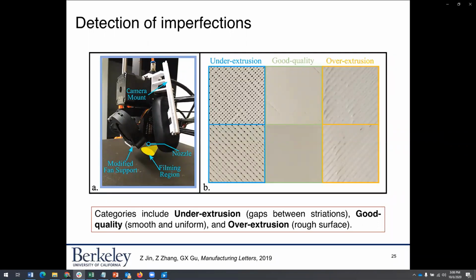Imperfections that may occur include under extrusion. So basically not enough material is coming from your nozzle, and so you see a lot of pores start to form. Over extrusion is another imperfection, where too much material is coming from your nozzle, and so you see areas start to bulge out, and the surface is not very smooth. And then we're also trying to categorize a sample that is known to be of very good quality.